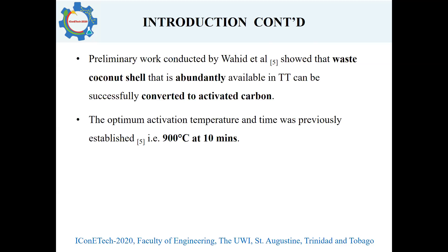To make activated carbon, in summary, you first have to carbonize the coconut shells in an inert environment, followed by the activation stage. The art of making an effective activated carbon lies in how you control the conditions of the activation process, such that the burn-off — the allowable loss of the product from carbonization known as the char — must be maintained at around 25 to 40% to yield a microporous activated carbon, based on previous studies. The activation temperature and time was established in this preliminary study to be 900 degrees Celsius at 10 minutes.